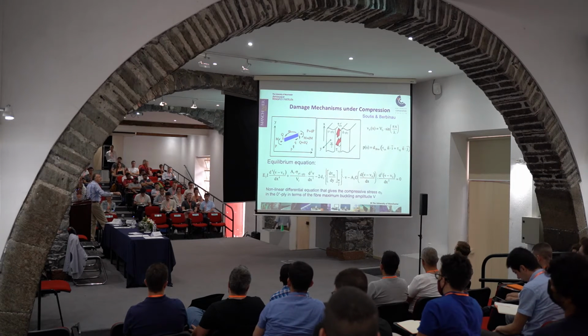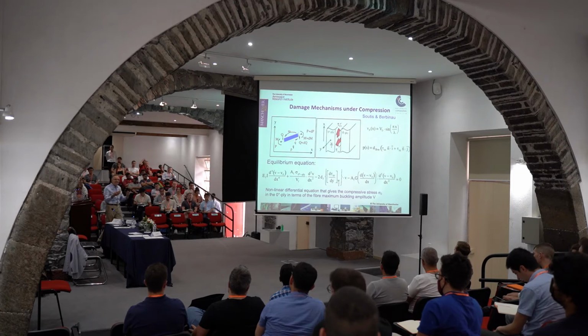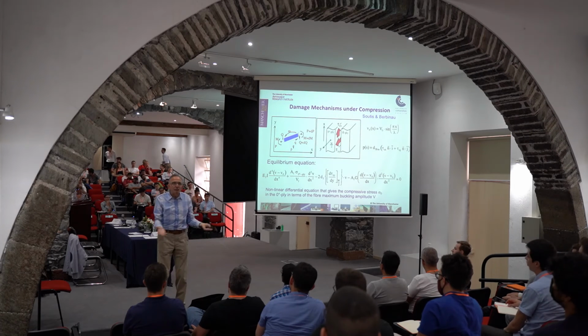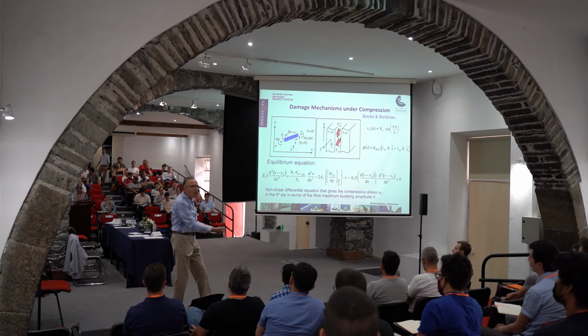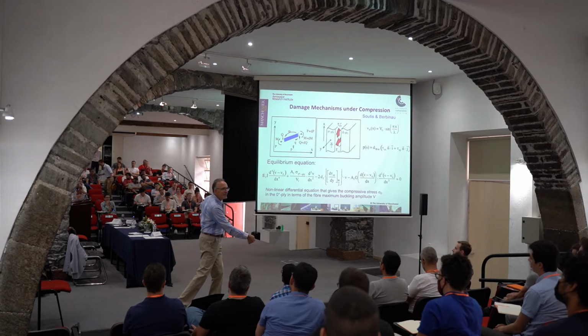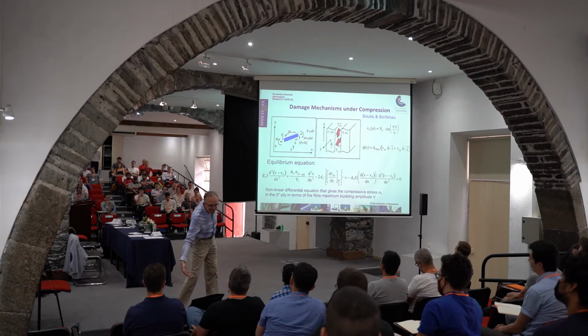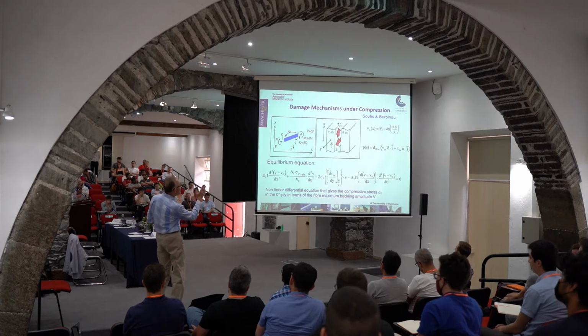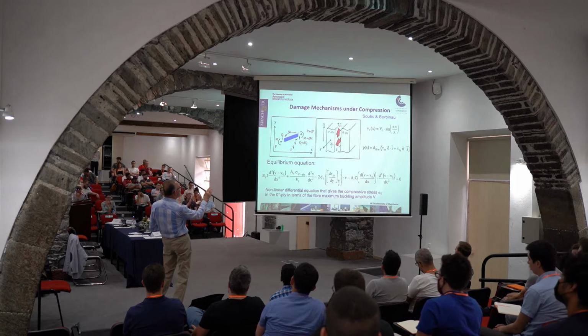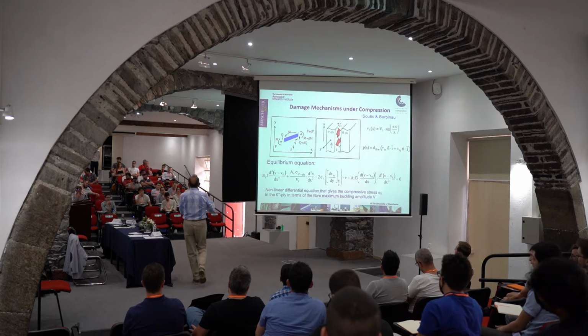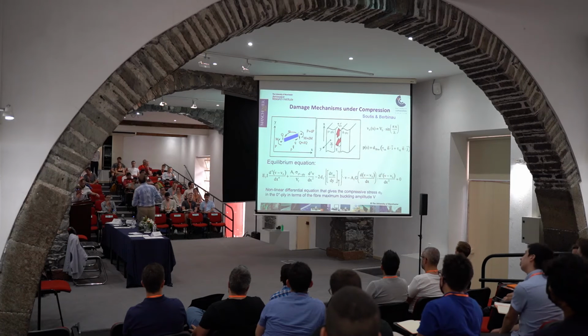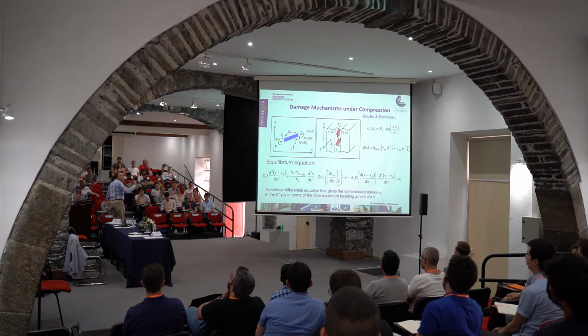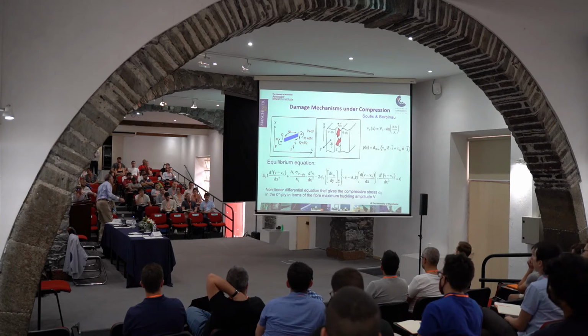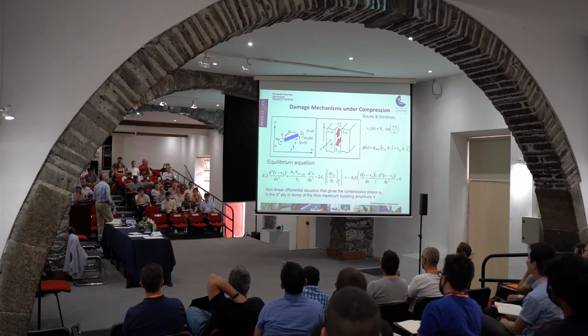And this step here are the interlaminar shear stresses developed at the free edge of the laminate. Because if you do a steel plate, if you're a civil engineer, you do the stress analysis of this, you don't care about stresses at the edge. It's a stress-free edge. But not in the laminated configuration. You develop those interlaminar stresses, the tau ZX and the tau ZY, especially the tau ZY, which is going to introduce additional waviness into my already wavy fibers. And it's going to destabilize those zero fibers, which is going to affect the stress at which fiber microbuckling will take place.